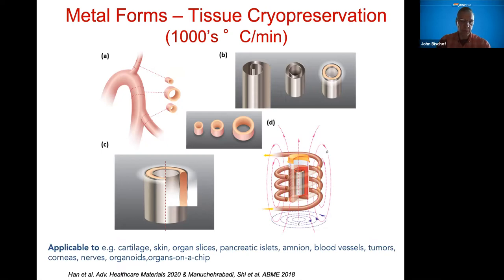This is much better than we can achieve with convection, which is just in the hundreds of C per minute. And it allows us then to do these thicker tissues, but it also allows us to actually load less cryoprotective agent in the thinner tissues because you have this more rapid rate. So it gives you both of these advantages.